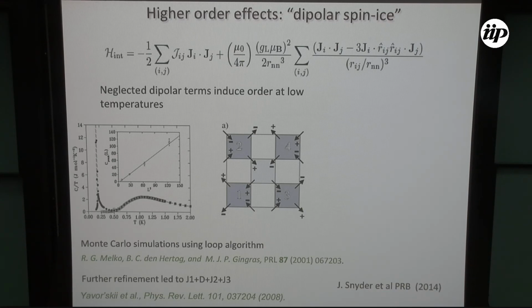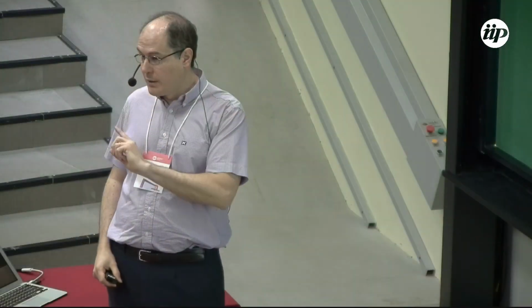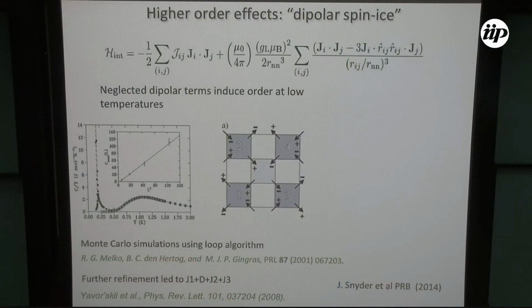And essentially, you see that it looked like Ramirez had stopped a bit too early. He should have gone a little further down in temperature, which is, of course, very easy to say later. But you can see that there's already a discrepancy there between the theoretical prediction and the experimental measurement. It was attributed to the fact that the parameters are not completely perfectly determined, so maybe this is slightly at a lower temperature, but it should be there. So according to the simulation, if this is the true Hamiltonian, it should be there. So what some people did was to take a whole bunch of experimental results and try to fit all those results with not just the dipolar and nearest neighbors, but to add dipolar, second nearest neighbor, and third nearest neighbor. And they saw that even in that case, you should get essentially the same kind of order.